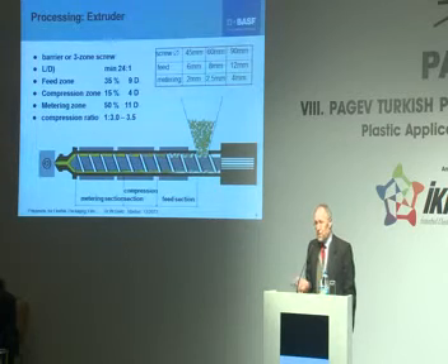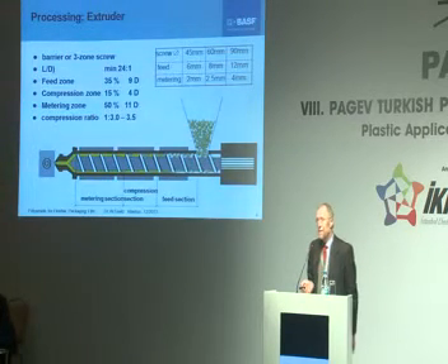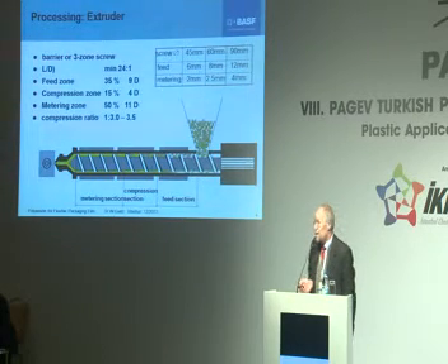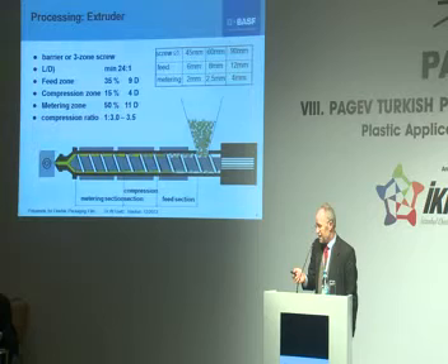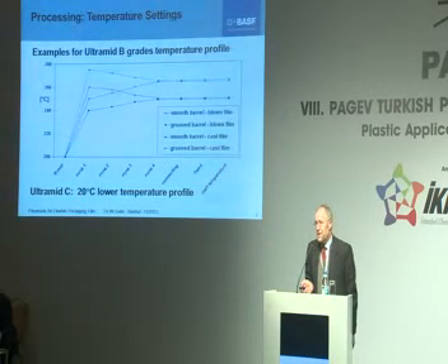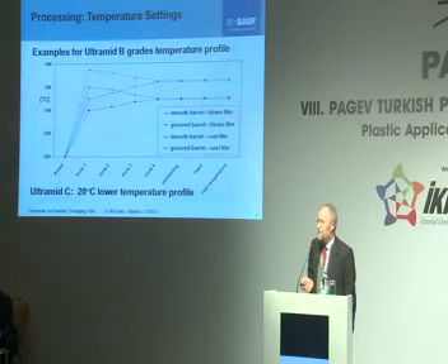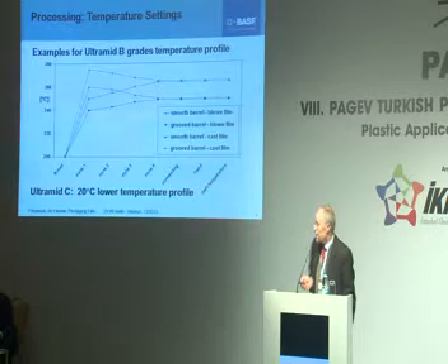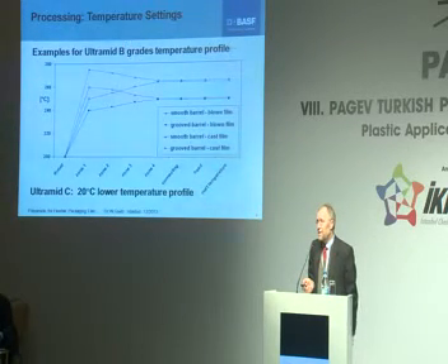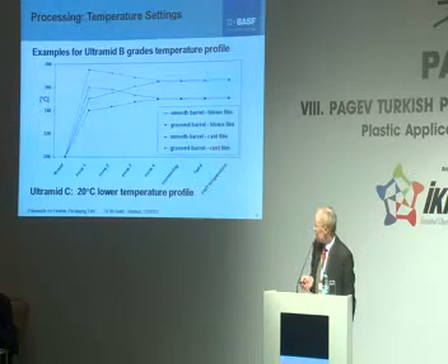Then, coming into the extruder, generally standard extruders of about the same configuration as used for polyethylene or polypropylene extrusion are used also for polyamide, usually with a relatively short compression zone with a compression factor of about 3. Generally standard extrusion lines can be used for polyamides too. Universal screws are applied in many cases. The temperature profile, of course, is much higher than in the case of polyolefins. Temperatures range in the area of 260-265 for cast film, about 250 for the blown film area, and starting temperatures may range even in the area of 270-275 for the feeding section.